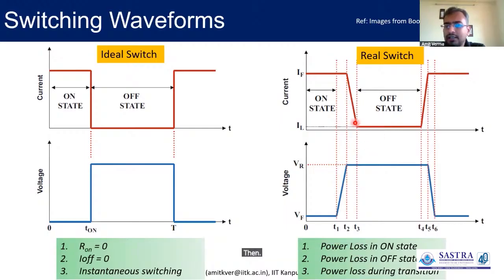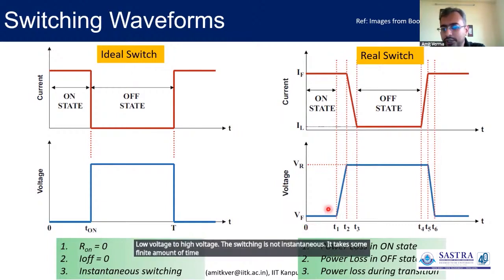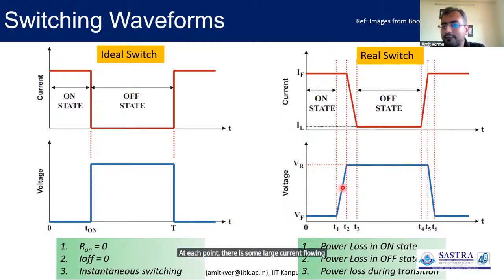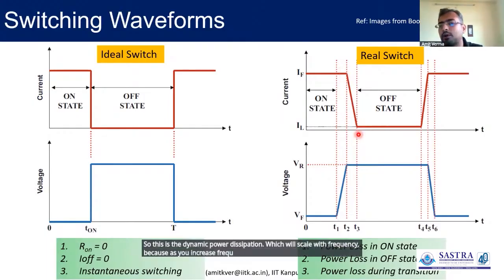Then when we are switching from high current to low current and low voltage to high voltage, the switching is not instantaneous. It takes a finite amount of time. During this time, at each point, there is some large current flowing and a finite voltage drop. Their product gives an instantaneous power, which we integrate over this transition time to get the power loss during the transition, off to on and on to off. This is the dynamic power dissipation, which will scale with frequency, because as you increase frequency, there are more off to on and on to off transitions.